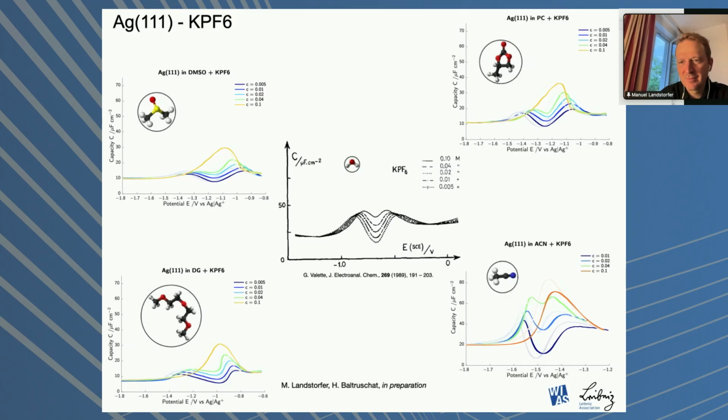But in principle, the trend remains the same as for water. Increasing salt concentration at a certain point yields that the minimum becomes a maximum. You will find that the capacity values for plus minus infinite voltage run to a constant independent of salt concentration.